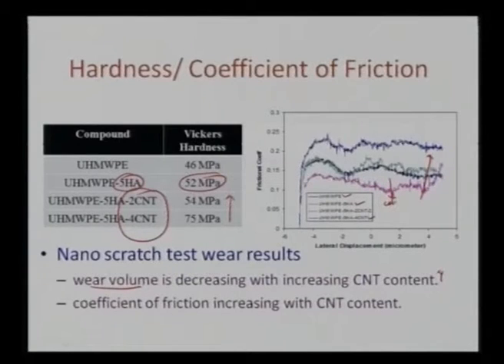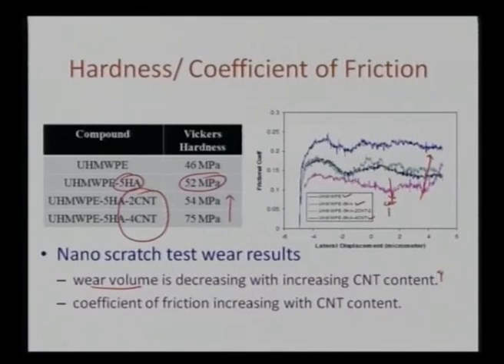That is happening because at nano level, once I am doing a nano scratching, there is a very poor interface between hydroxyapatite and polyethylene. So as soon as I am putting my indenter tip, it is very easy for the indenter tip to blow away the material on the side. So there is very little lateral force in comparison to the normal force. That is the reason I am seeing much reduction in the coefficient of friction for the 5% hydroxyapatite.